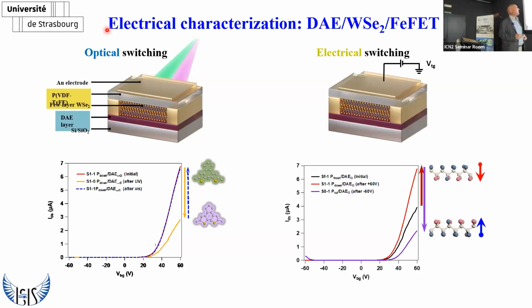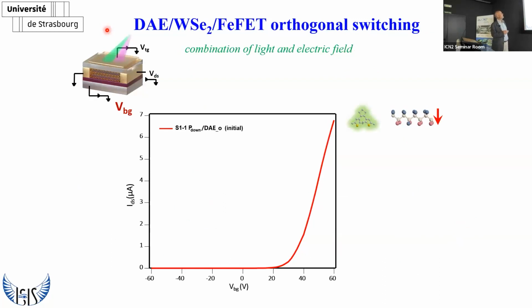Likewise, in this kind of device, we could use the control with the electric field applied between the top and the bottom electrodes in such a way as to control the alignment of the dipoles, from the case where we apply plus 60 volts, where the dipole is pointing down and we have the highest current possible, to the case of minus 60 volts, where we have the dipole pointing up. And here as well, we have a change in the current of about 65 to 70%. So this is the plot that combines the two stimuli.